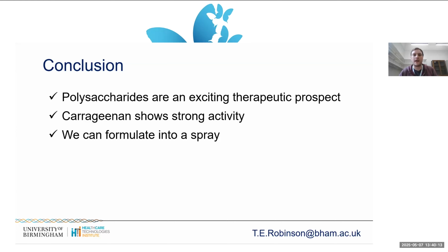So honey is interesting. Honey actually isn't a polysaccharide. It's a very, very concentrated solution of monosaccharides and disaccharides, which is why the concentration of sugar is so high. I mentioned that with the polysaccharides, we've got less than 1% to create that structure. Honeys get well up into the 60s, 70s, 80% sugar to create the same amount of structuring. Same with syrups and things. But yes, there's absolutely no reason why you couldn't incorporate other things into these. As I said, they're 99.5% water, so anything water soluble would absolutely fit into these materials.